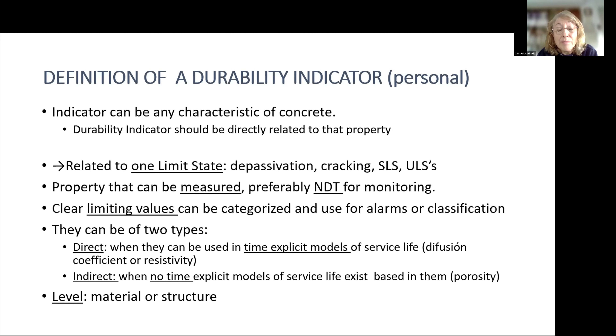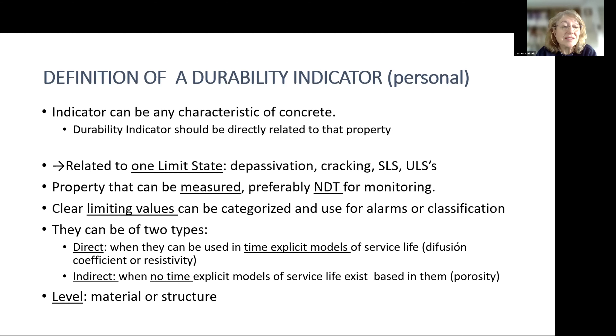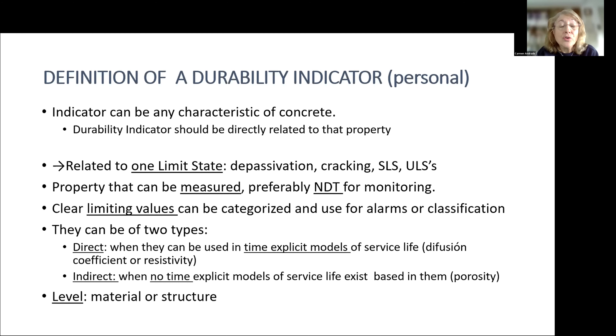The other aspect is a property that can be measured. In my case I prefer non-destructive monitoring, because then you can monitor in the structure — not only the material, but the structure itself. Resistivity can be measured in both cases. It has to have clear links, as presented by Veronique, Roberto, and Mark — limiting values that can be categorized and used for alarms or classification. This is distinct from modeling: in modeling you calculate the precise value, but when dealing with an existing structure it is helpful from an engineering point of view to have categories, not only exact values.